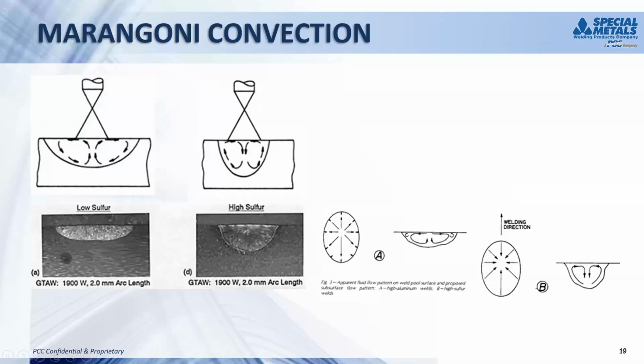But one of the things that's kind of different about this is what causes the difference in penetration. And it's good to know. It's called Marangoni convection. And basically what causes fluid flow in the puddle itself is either the surface active elements or lack of surface active elements. And if you notice, we said before, nickel alloys, low sulfur is terribly important. If you look at the specifications for nickel alloys versus steel, steel is typically .02, .03 sulfur. Nickel alloys are .002, .003 sulfur. Sulfur is a surface active element. And when you have sulfur, like in a steel alloy, it acts as a surface active element, and it increases the surface tension of the pool.